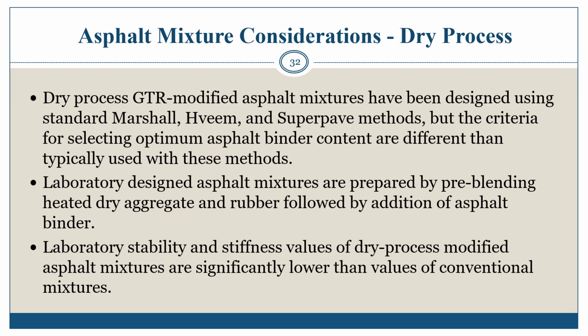Asphalt mixture considerations for the dry process. Dry process GTR modified asphalt mixtures have been designed using standard mix design methods. Criteria for selection of optimum asphalt binder content may be different than typically used in these methods. Laboratory designed mixtures are prepared by pre-blending heated dry aggregates and rubber followed by addition of the asphalt binder. Laboratory stability and stiffness values of dry process modified asphalt mixtures have been reported to be lower than values of conventional mixtures.